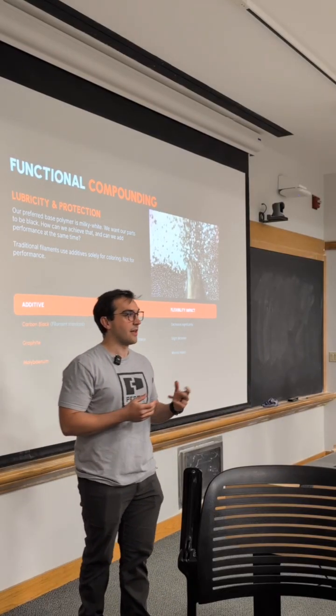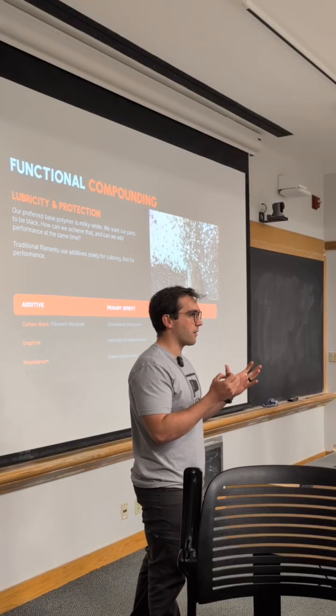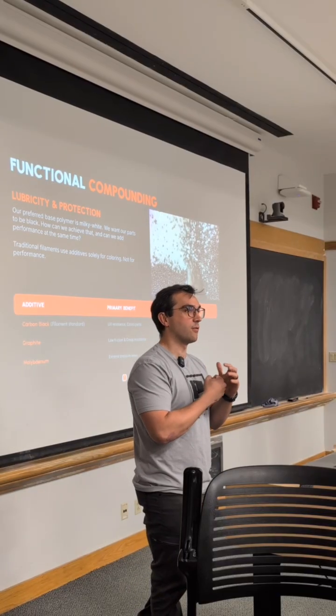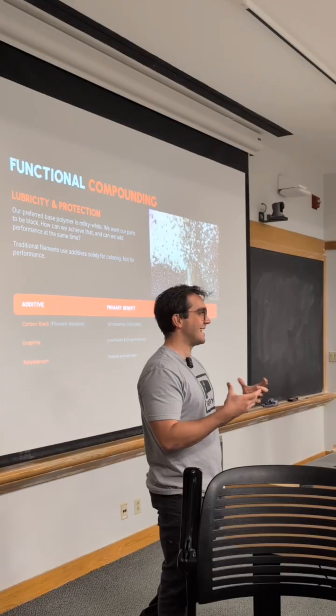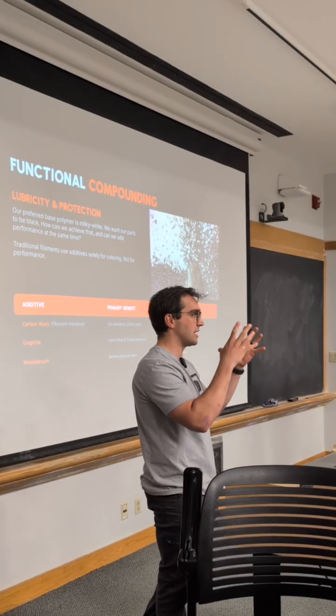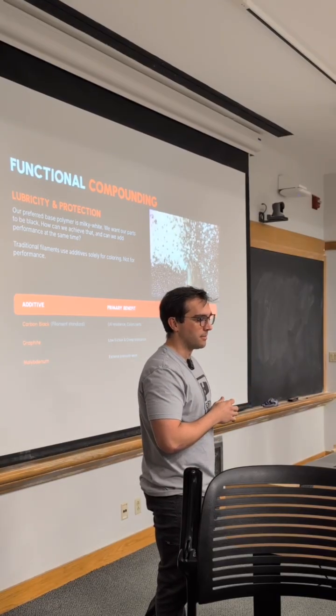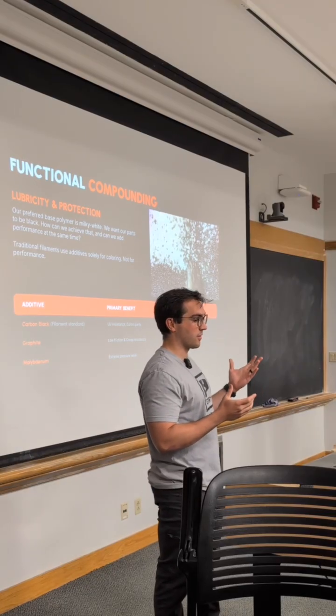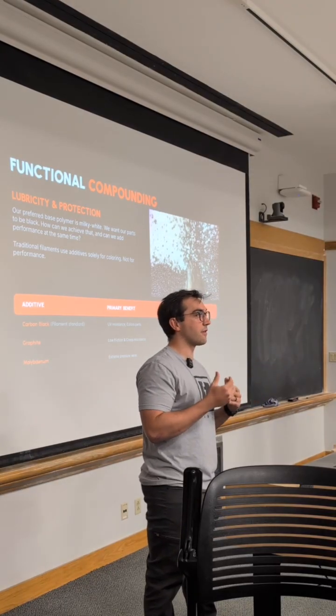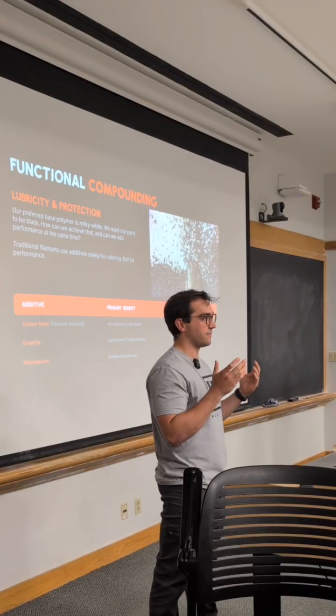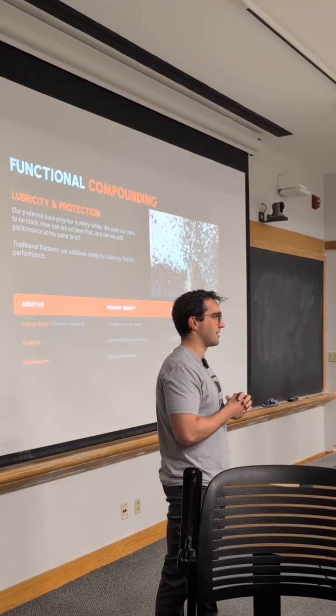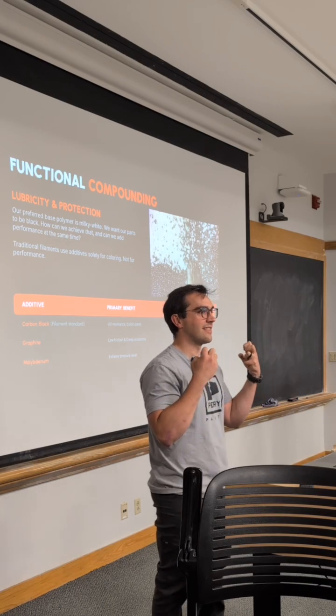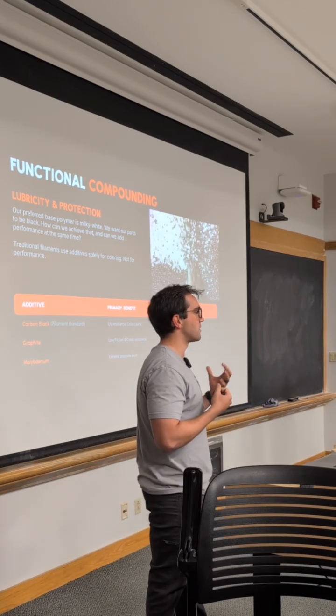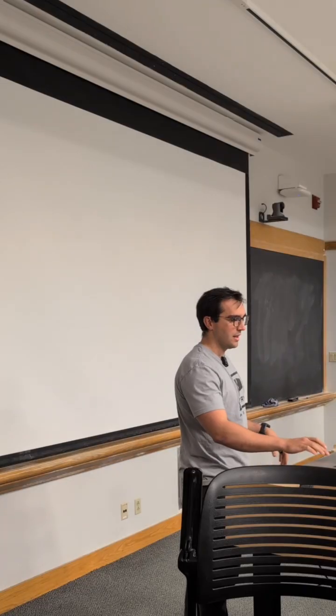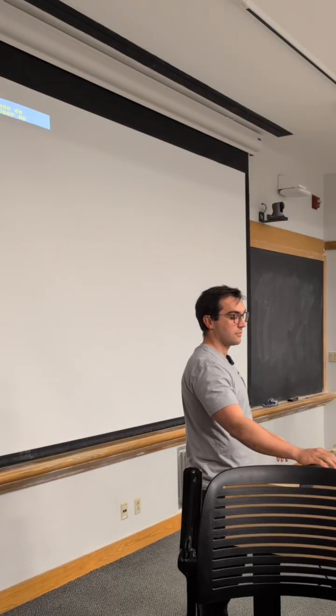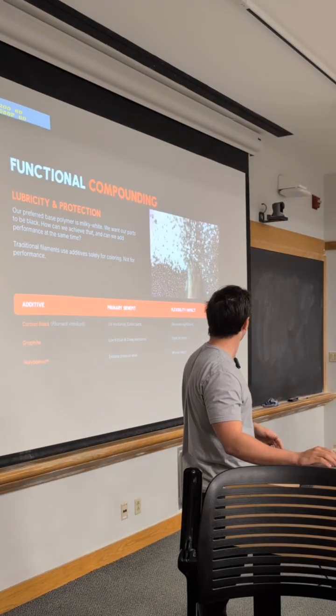So graphite has super low friction, and as the part wears, as the TPU abrades away, you're exposing more graphite inside the part, basically in suspension in that polymer. It also gives you some creep resistance, and the biggest thing is it has a very minimal impact on part flexibility. So the graphite doesn't really, it's not very stiff or rigid inside that matrix, and it allows the part to flex more reliably.